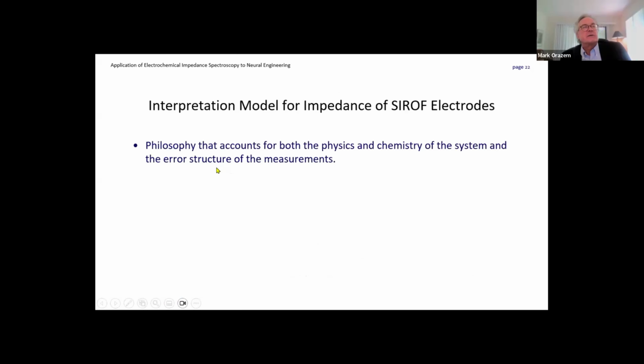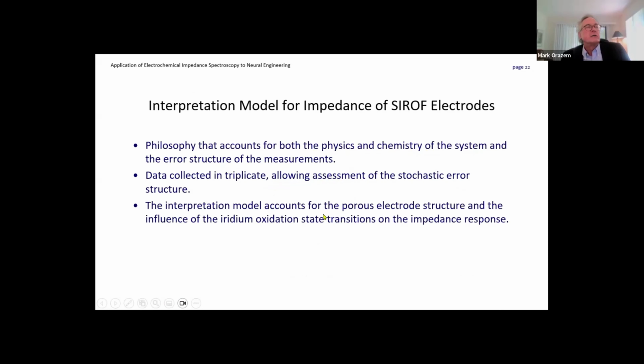So our approach is this. We want a philosophy that accounts for both the physics and chemistry of the system and the error structure of the measurement. The data are collected in triplicate, allowing us to assess the stochastic error structure. And the interpretation model accounts for the porous electrode structure and the influence of the iridium oxidation state transitions.